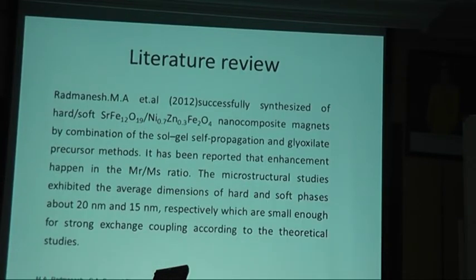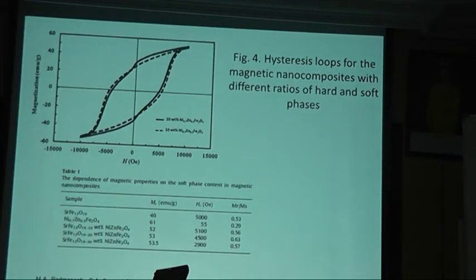Okay, next is Radmanesh. Previously they used barium ferrite, and this one they use strontium ferrite and again nickel zinc ferrite. In this case they use sol-gel, and they can go down to hard ferrite 20 nanometer and soft ferrite 15 nanometer in sol-gel. Okay, this is the graph.